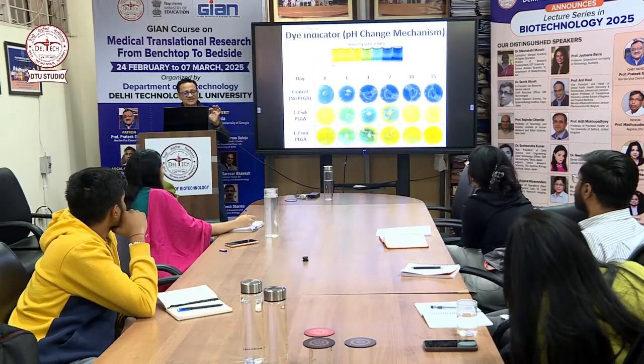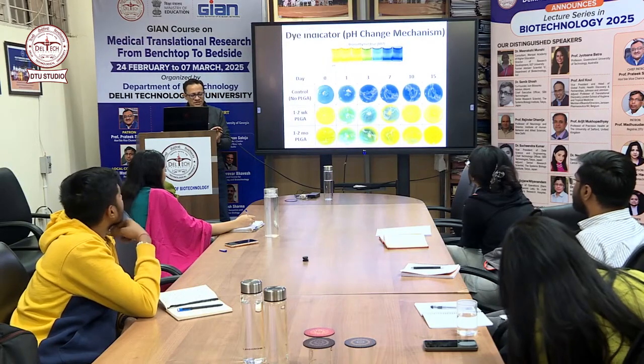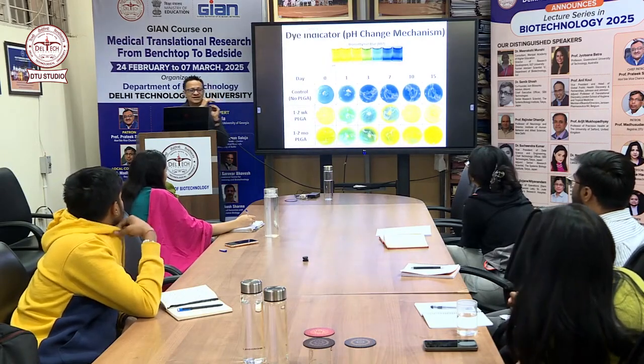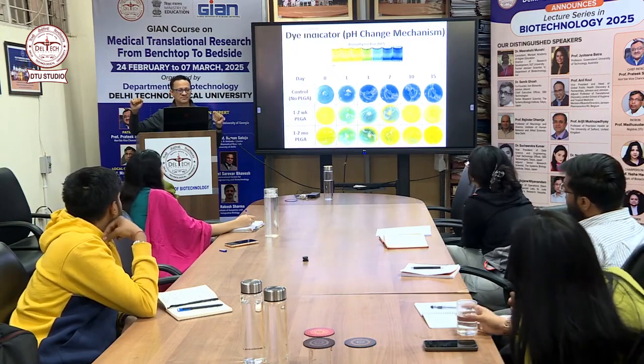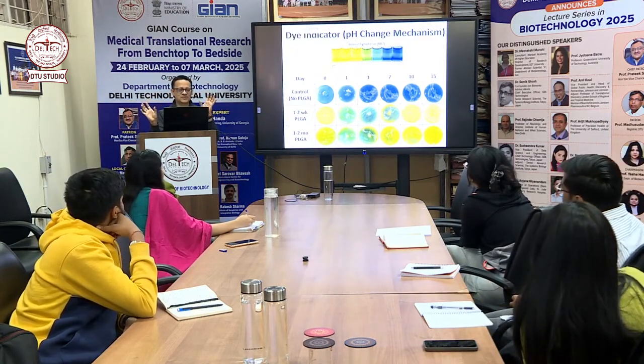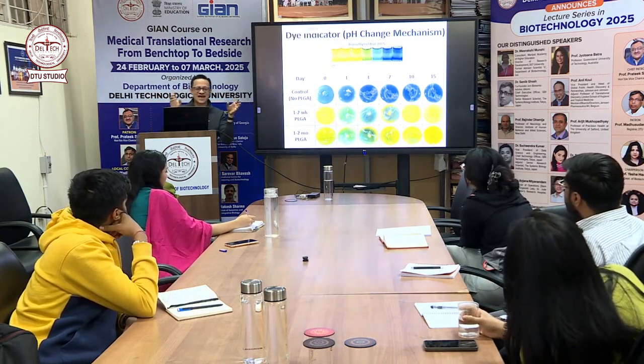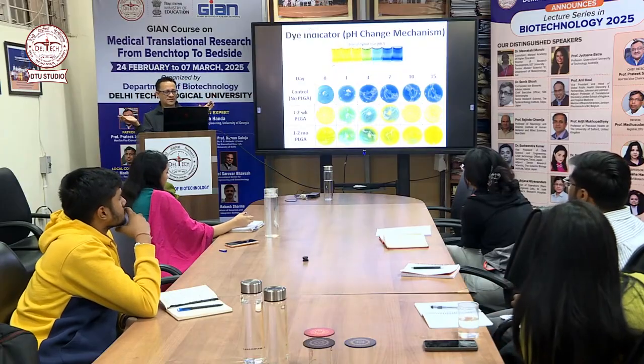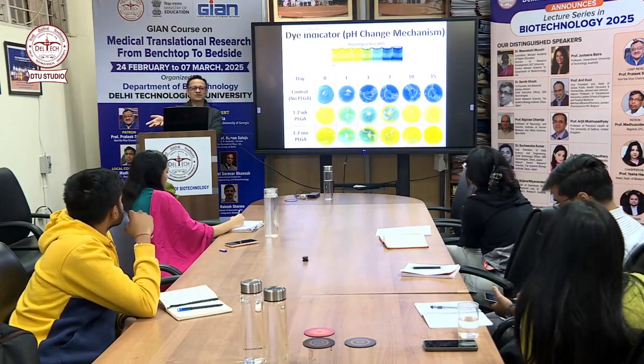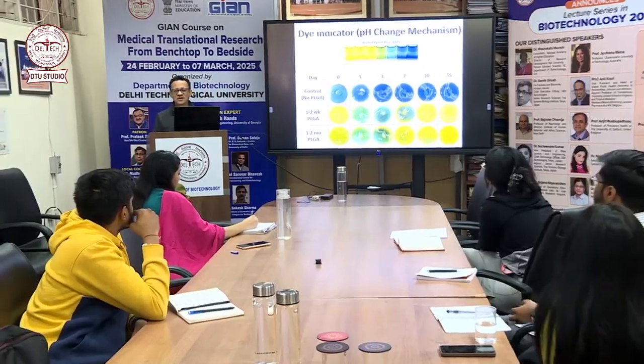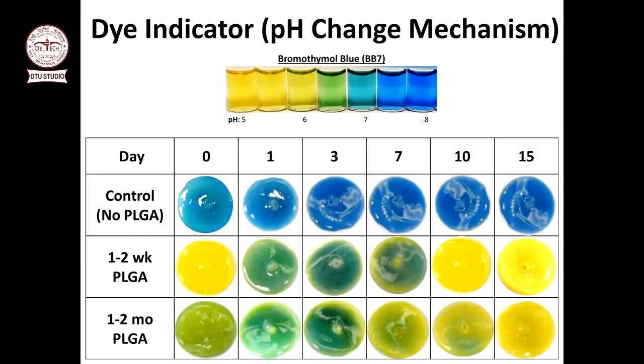But when we had this 1 to 2 month PLGA, the coating remained greenish for a very long period of time, because there was a very nice balance between NO release and PLGA breaking. A really good application of this is if you have a catheter in a hospital setting and you tell the doctor, if this catheter turns yellow color, that means NO release has died. That means all the NO donor is gone and you just have a yellow color now.